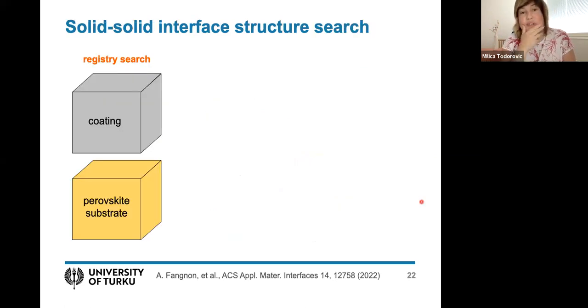Another thing that we were interested in is how to do structure search for solid-solid interfaces. Our colleagues were looking at perovskite substrates, which are unstable in air, and they need some kind of coating material to protect them. They found some good candidate coatings, but they didn't know how best the coating and the substrate would adsorb to each other.